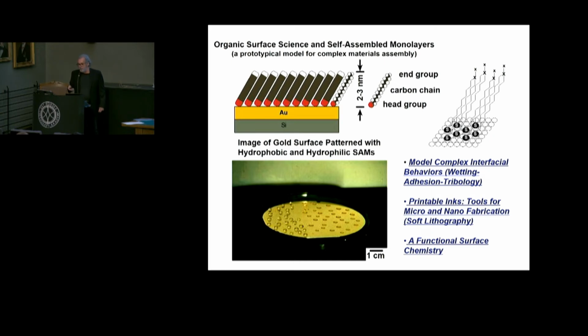So we'll move on and go back to the original story again. And that is, we have modifiable interfaces and we can show, and I think the picture at the bottom was from George originally, the earliest example of a patterned substrate in which half the wafer was dunked in something hydrophilic producing a SAM, and half of it dunked into something on the hydrophobic side. You see the drops placed on it show different contact angles for these water drops in contact.